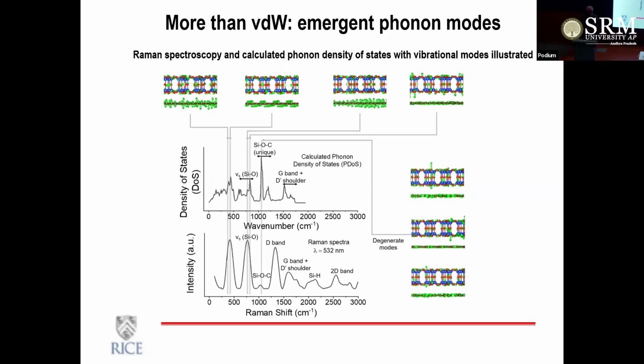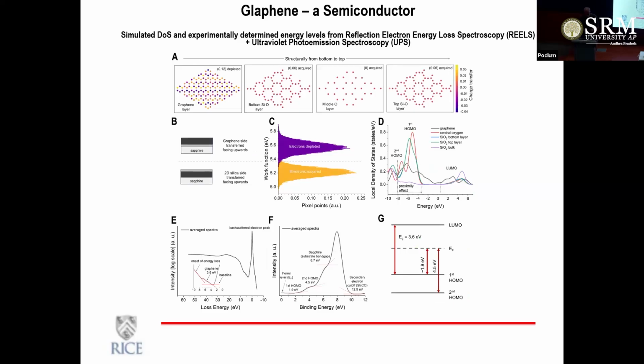And one could think about all kinds of hybridization that you can build from materials of such different nature. I can hybridize an insulating material and a conducting material to get something in between. In fact, in this particular case, it seems to be a semiconductor. You can use techniques like REELS and UPS to get information about the band gap. And in this particular case, the band gap comes out to be 3.6 eV, which is a wide band gap material. So again, it's another kind of engineering.